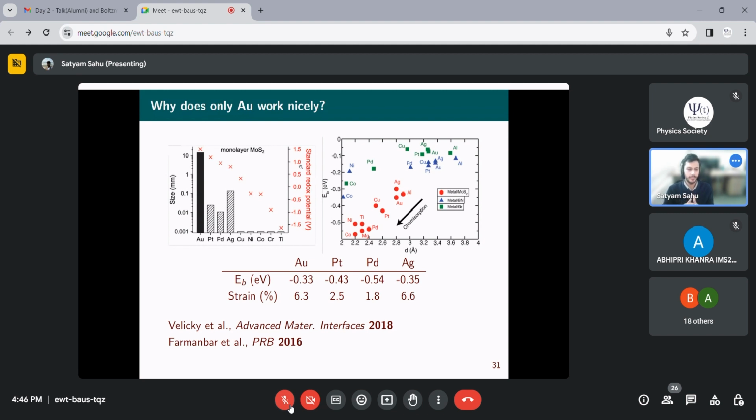If the metal has the high standard redox potential, that means it does not react much with the environment, or it does not react at all. So as you reduce the standard redox potential, as you can see here, the material starts to react with the atmospheric contaminants, and as a result of which you see that the yield is decreasing.